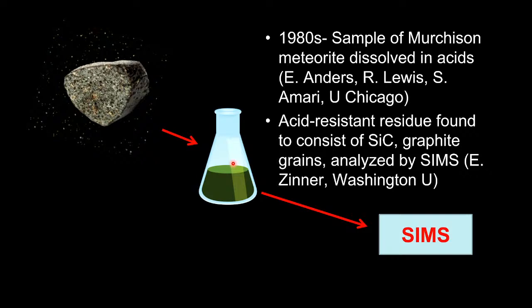So it's like burning down a haystack to find a needle. And what they found was that they dissolved everything else. What was left was a little vial full of silicon carbide grains and graphite grains. And they were analyzed at Washington University by SIMS, by my PhD mentor, Ernst Zinner. This technique was just coming alive at that time.